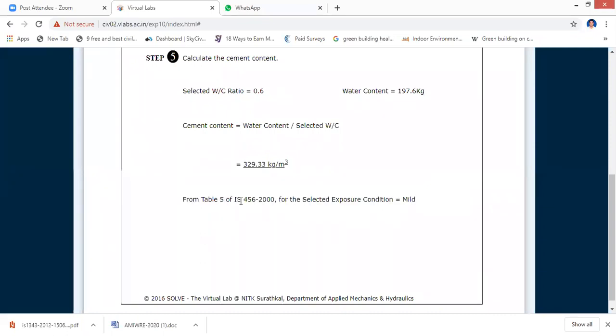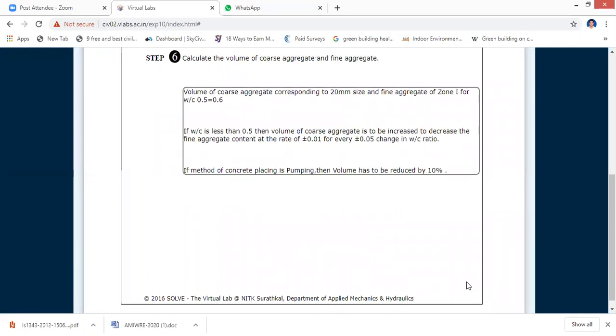So from Table 5, IS 456:2000, for the selected exposure mild, we get the minimum cement content and the minimum water cement ratio. So the 329 kg per meter cube is the cement per cubic meter which we are using, which is greater than 300, which is the valid one, right? So then, okay. And the volume of coarse aggregate corresponding to 20 mm size and fine aggregate of zone 1 is 0.5 to 0.6.